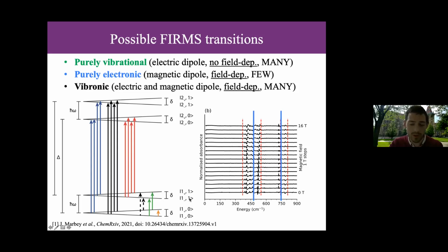So that's purely vibrational. And then these black dotted ones here are the intra Kramer's doublet vibronic transition. So we're going from the -1 to the +1. So we're doing an EPR transition associated with also a vibrational excitation. So these black ones are the vibronic ones that we're interested in. Now, we know, of course, the 0 field, no vibrations, ground to first excited Kramer's doublet from luminescence. That's 470 wave numbers. That's that blue line.